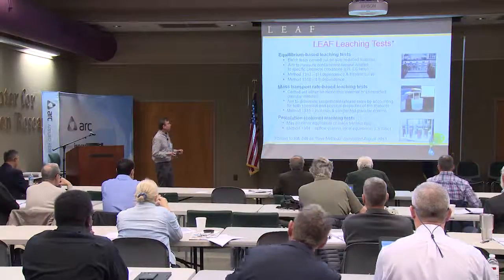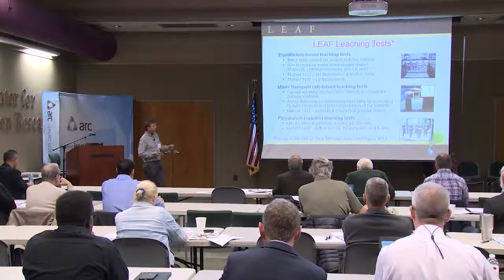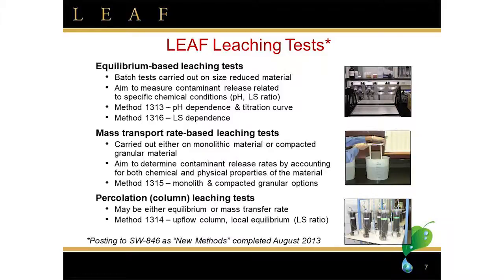And I'll talk more about that later in terms of the work that we're doing with Kent. So David touched on these already. There are 4 basic methods in SW 846, LEAF methods, EPA methods. You've got 1313, which is a pH dependence model, so release is a function of pH. You have 1316, which is release as a function of liquid to solid ratio. You have mass transport rate tests. David talked about the 1315 test. And then you also have some percolation column leaching tests, which we're just engaged with doing the software quality assurance for those models now, where it's an upflow column looking at the local equilibrium and the liquid to solid ratio.